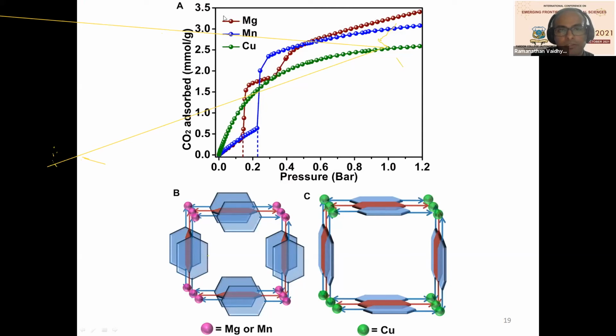Whereas the same gating pressure for manganese is at a higher value, because here it is a little harder than magnesium, which means you don't need a lot of force to open the gate. It is very easy to open the gate of magnesium, whereas for manganese you need a little bit of force. Whereas copper, which is very soft, you don't need any force. It is always open, so you don't even see a step in the isotherm. So you are beautifully able to control this gating phenomenon by using hard-soft gate control. That is what we call hard-soft gate control.